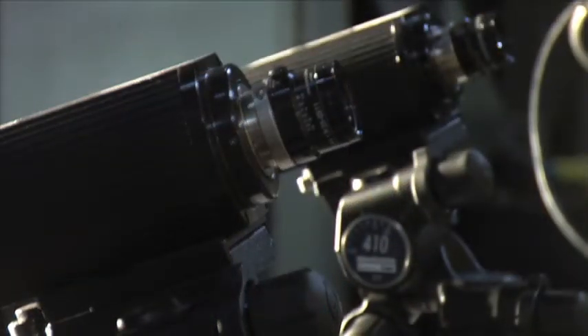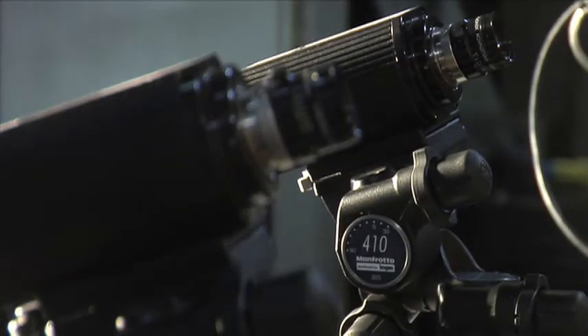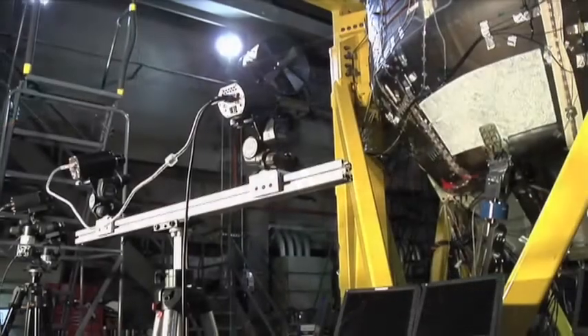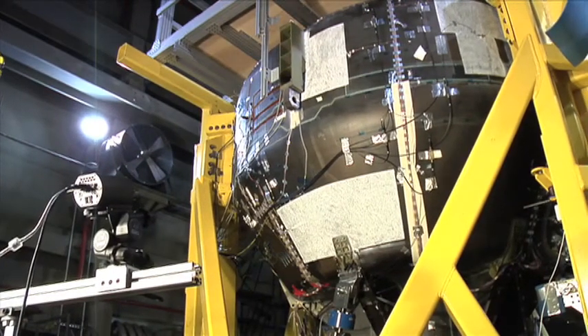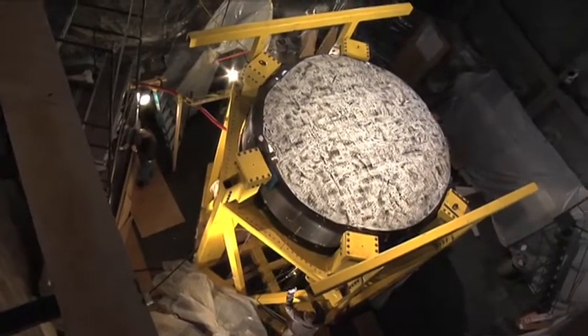The tools we use are anywhere from a tensile testing machine pulling on coupons to get their strength and specific stiffness, to some pretty high-tech imaging methods to get full field strain of a complex article, to look at failure modes where things start to break apart. Other techniques, a lot of times we'll do chemical analysis to figure out whether a process has developed like we expect. Like the cure of a composite resin, you can evaluate it chemically to see how far it's progressed. And that's often important to make sure that you control processes at the coupon and full scale level.